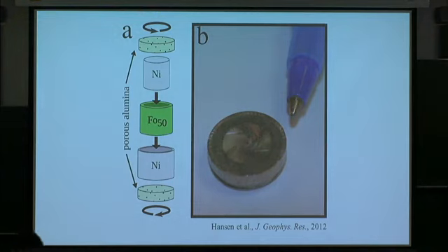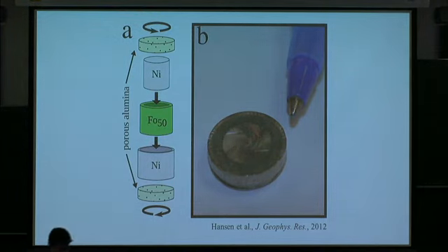Okay. And so for working on olivine, we designed a sample geometry like this, where we're actually working on thin-walled cylinders of olivine. And the benefit of this is that it simplifies the mechanics of the test. And so we have this ring that we're twisting, so it's effectively an infinite shear zone.